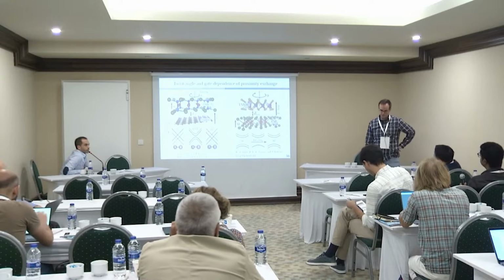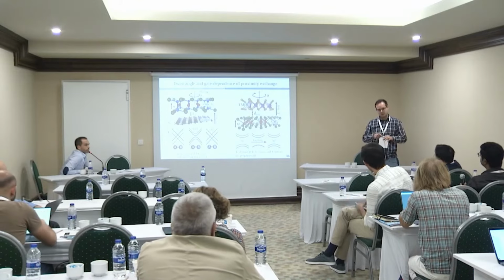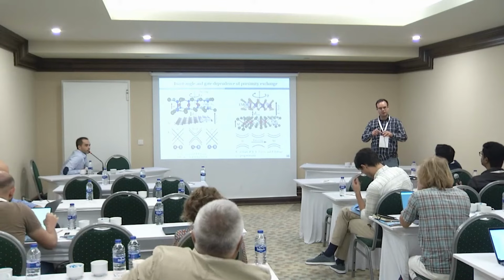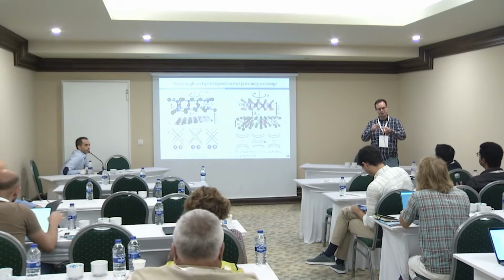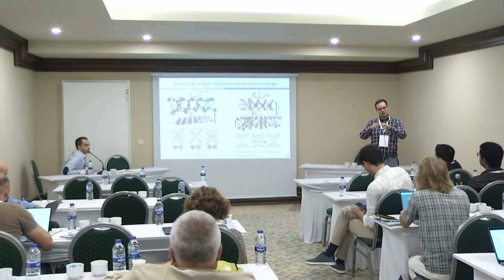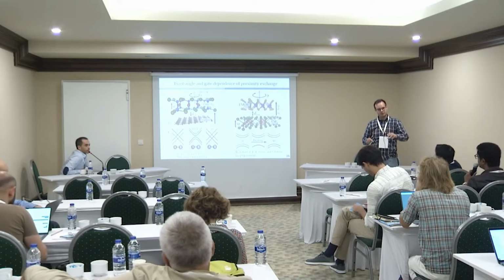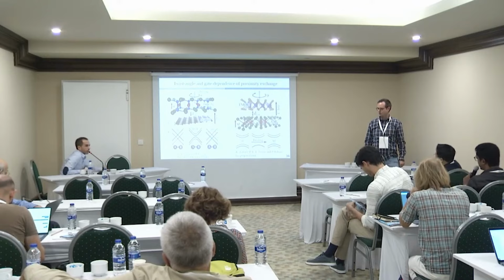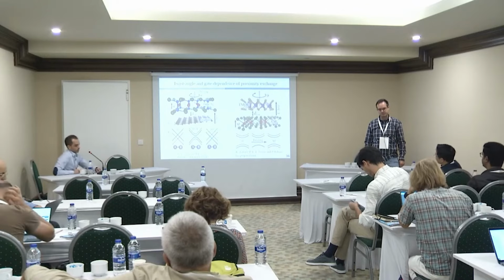I guess what happens once you shift, say, the Dirac cone within the band gap, you can tune the proximity. For monolayer graphene, there is no band gap. No, within the band gap of the TMDC. So you shift your Dirac states within the band gap, and thereby you affect the proximity spin orbit coupling. How will it depend? We are running out of time, so probably we can discuss offline. Okay, sure. Thanks again.